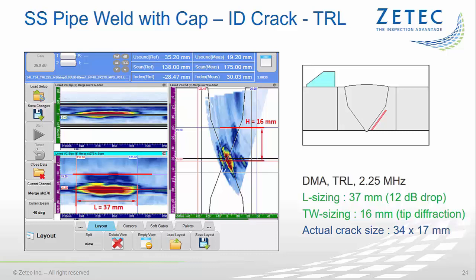In this case, we have compared the 6 dB drop and the 12 dB drop techniques. The 6 dB drop sizing result was 26 millimeters, and the 12 dB drop technique found a flaw length of 37 millimeters, compared to the actual length of 34 millimeters. The result of the 12 dB drop technique is to be preferred because it is more accurate and, in addition, a conservative assessment of the crack.